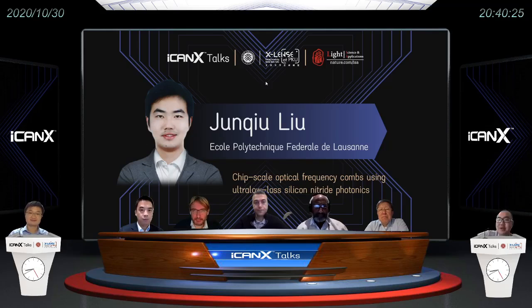That's a very, very good question. Actually, I didn't mention this in this talk, but you're absolutely right. Usually you want to get the best silicon nitride from the LPCVD process. However, due to the surface chemical dynamics and the temperature difference between the deposition temperature and room temperature, you will have a huge tensile stress in the silicon nitride. Therefore, maybe you don't see my screen, but we have to actively make some filler patterns. If you see my screen, you see we have this kind of checkerboard filler pattern. This pattern modifies the surface topography of the silicon nitride film, such that the stress is not accumulated over the film plane.